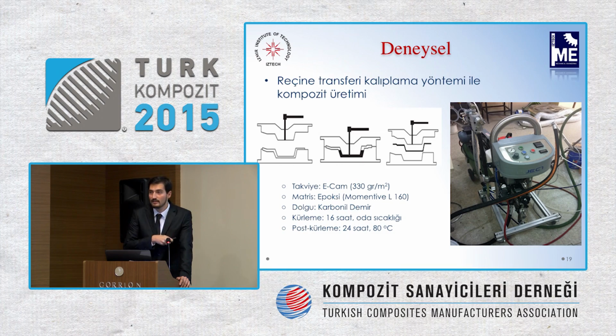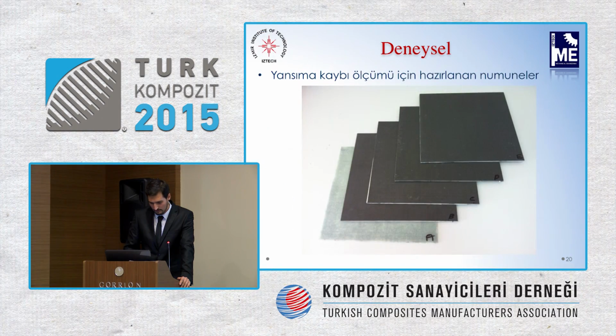We pressurize the material in a closed mold, and we produce the desired model. As I said, I use glass as a reinforcement. As matrix, epoxy is used, and its model is L160. As a filler, we use carbonyl iron. The curing was done at room temperature for 16 hours, and post-curing for 24 hours at 80 degrees Celsius.